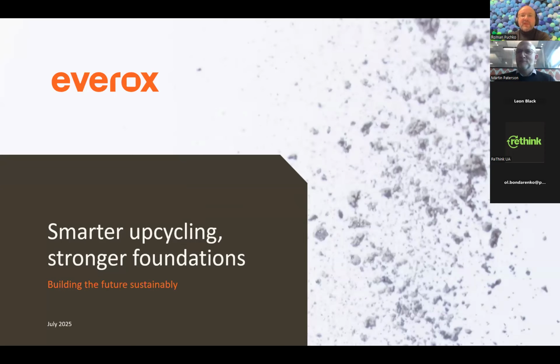I'm very happy to be here. My name is Martin. I'm co-founder and chief commercial officer of Everox. And also thanks to Leon. I only could listen in the last minutes, but I think you did half of my job already by explaining all the good benefits of the recycled cement paste and how we can use it further. For us at Everox, this is of course the key. The key of our process is basically to separate the old cement paste from the aggregates as much as possible, and then activate the cement paste afterwards again, so we can use it as an SCM.